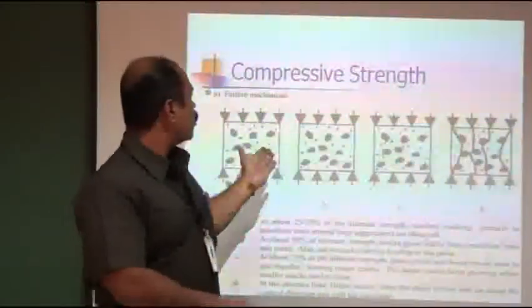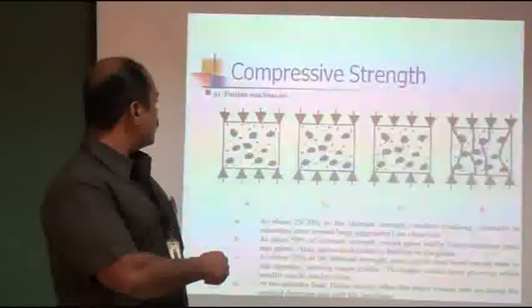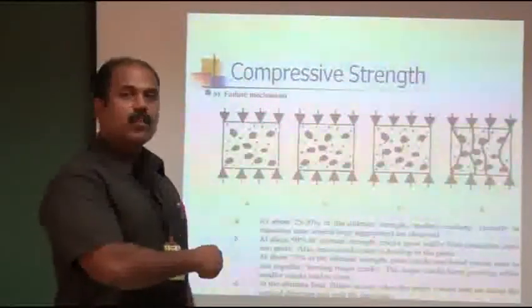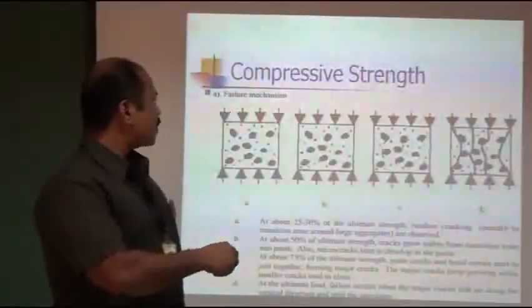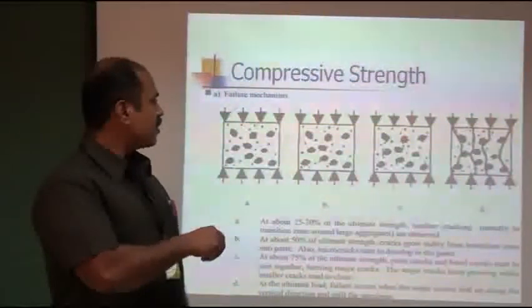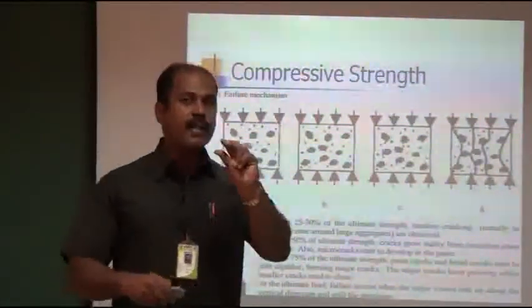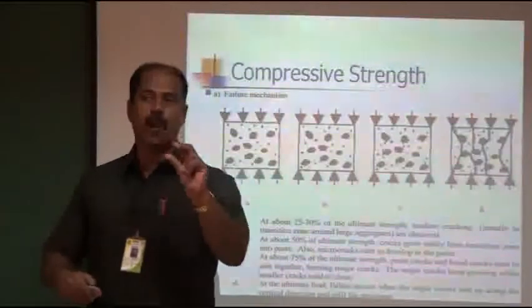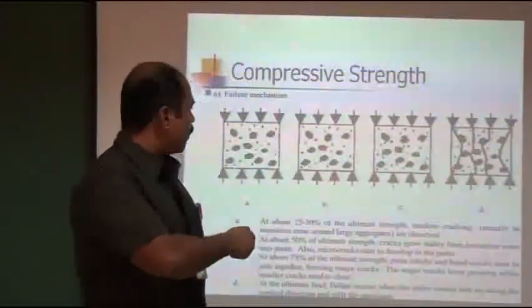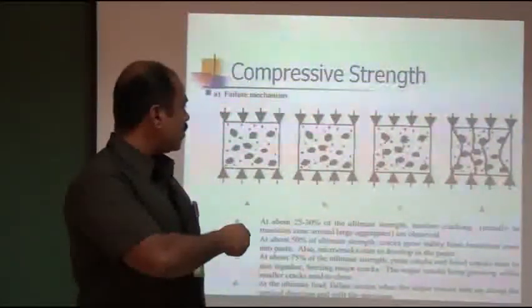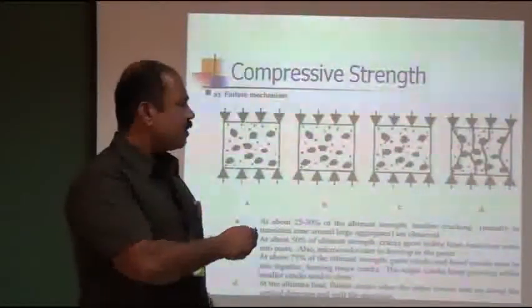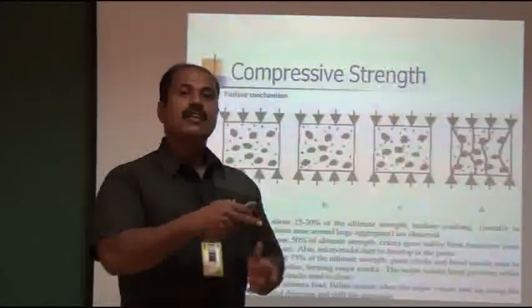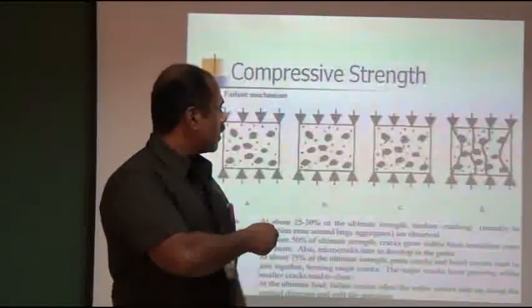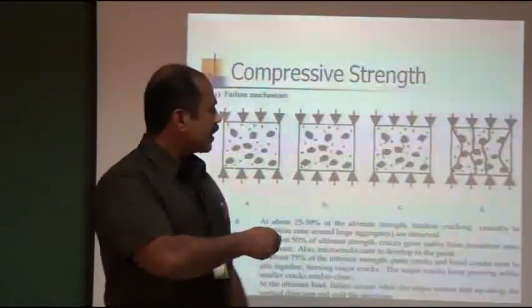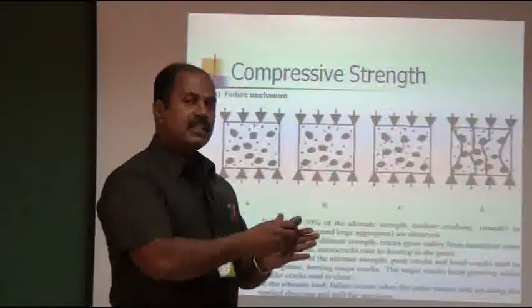So how do we do the compression test? As per the Indian Standard, the cube is 150 by 150. When we apply compression, cracks will form. First the crack starts at the joint between the coarse aggregate and the fine aggregate mortar. So first the crack develops at the bonding of the coarse and fine aggregate. Then the crack slightly enlarges to reach the second aggregate. Finally the crack reaches from the top to the bottom surface, and the concrete splits easily. That is the procedure.